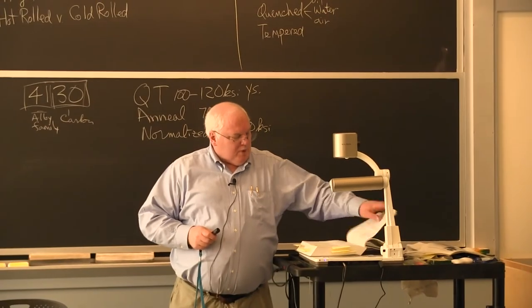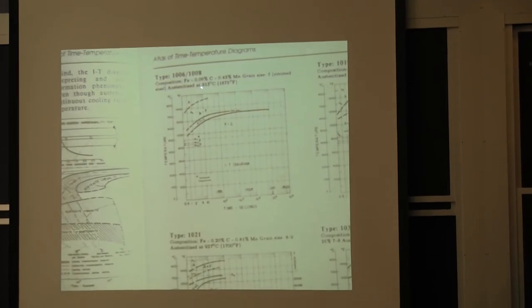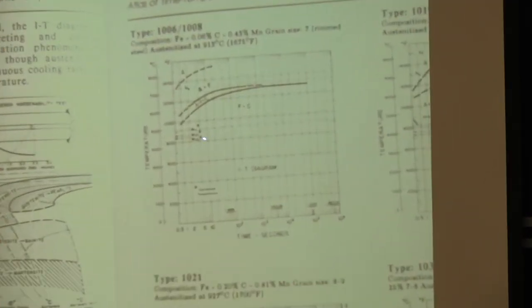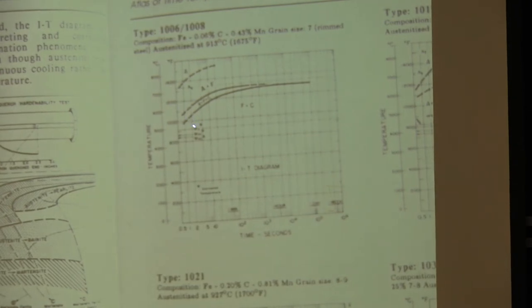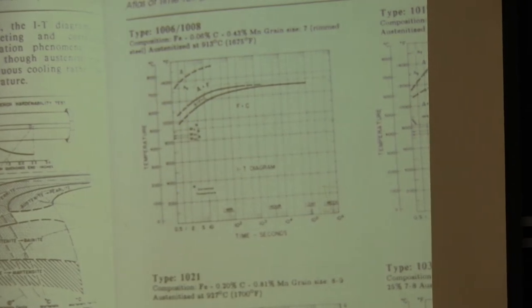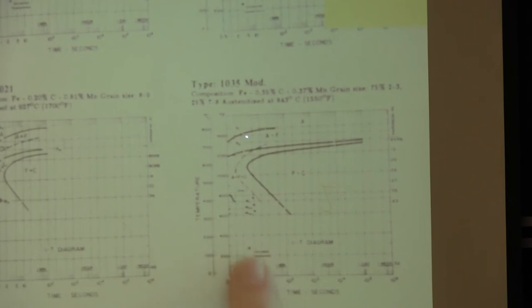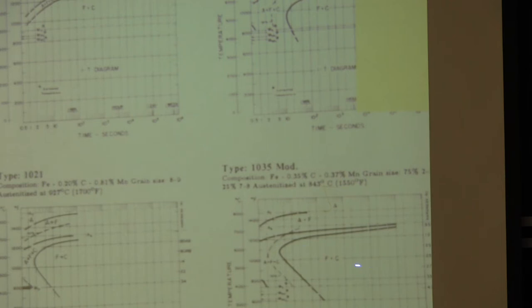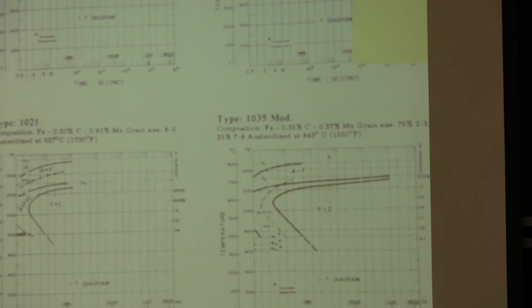But if you look at lots of different types of steels, you see that for a 1006 or 1008 steel, these things are transforming in less than 1 or 2 seconds. If I add some alloy content, this is a 1035 steel, and the C-curve is pushed over to longer times, but I'm still dealing with times of less than 10 seconds for the transformation. If I get clever, I can start adding alloying elements.